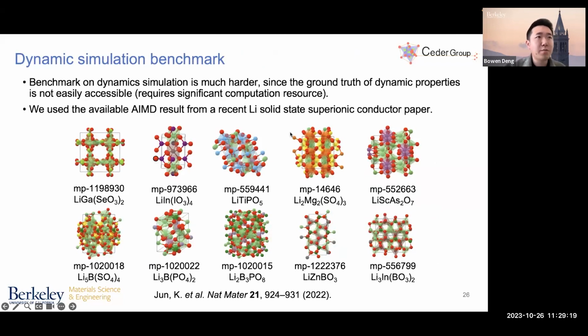Besides this benchmark on new materials discovery, we're also interested in seeing whether we can apply pre-trained foundation models like CHGNet to simulate dynamic processes reliably. But these dynamic process benchmarks are noticeably much harder than the benchmark for new materials discovery, since the ground truth of these dynamic properties is not easily accessible. You should know that simulating just a single diffusivity of one of these materials typically requires several weeks and up to months. So we use the available AIMD results from a recent lithium solid-state superionic conductor paper, where the previous researchers studied the ionic diffusivities of 10 different types of lithium superionic conductors.